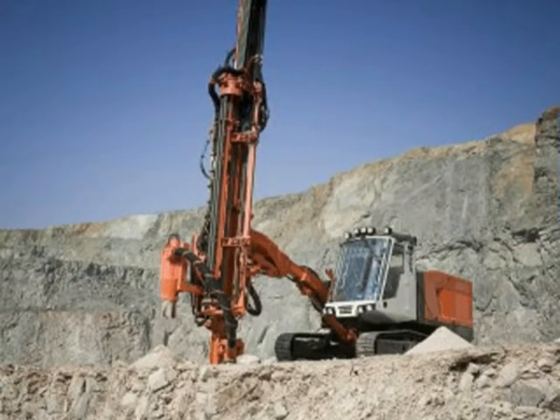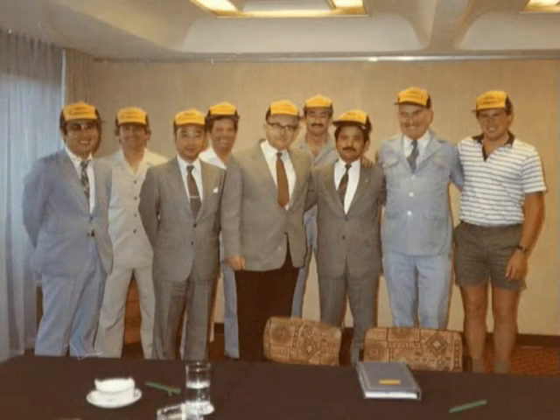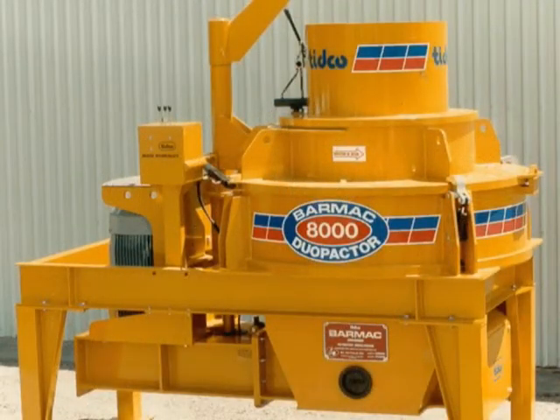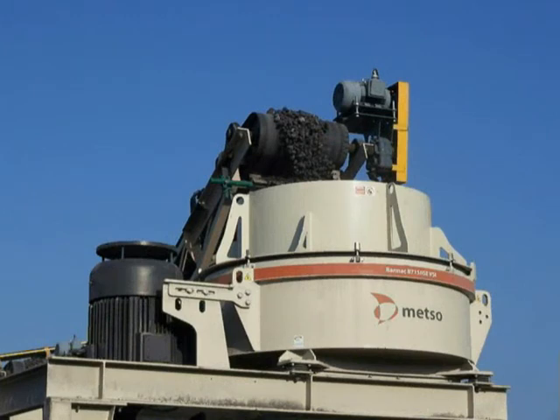The idea of using tungsten carbide came up. We had four-inch diameter quarry drills called Halco drills, which had tungsten carbide in the form of a cross — four quite heavy-duty pieces able to stand up to down-the-hole hammer work. We took the tungsten carbide bits out of the old drill bits and put them in, and that moved the wear time from the two and a half hours Jim was experiencing out to six weeks. Six weeks meant commercially viable, and that was quite a breakthrough. From then on it was a commercial goer, and we shared the patents and went on from there.